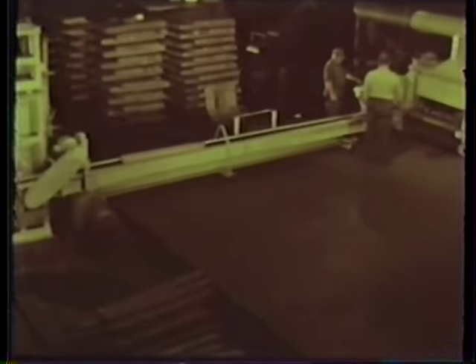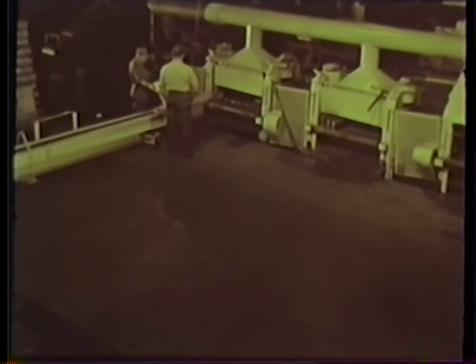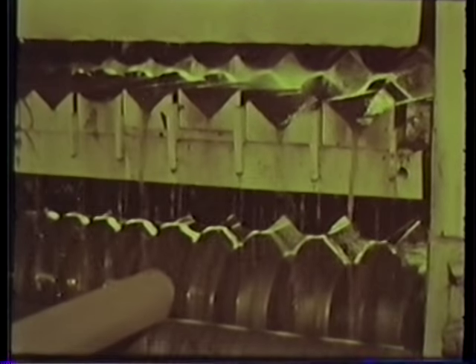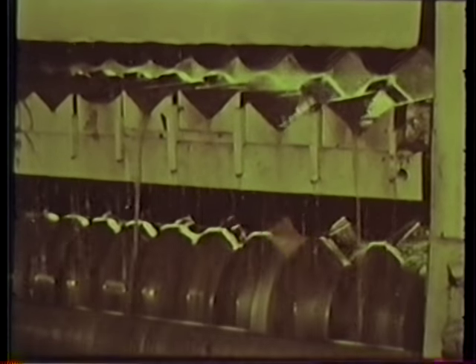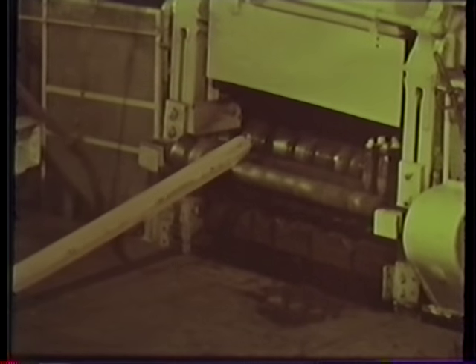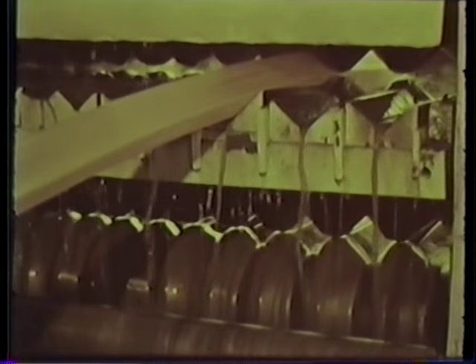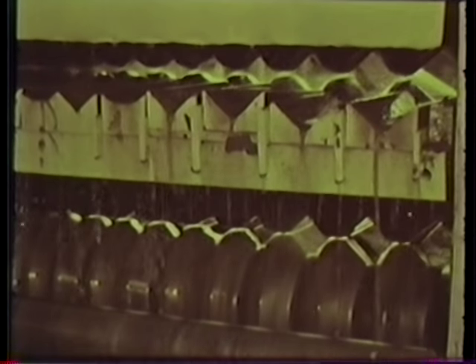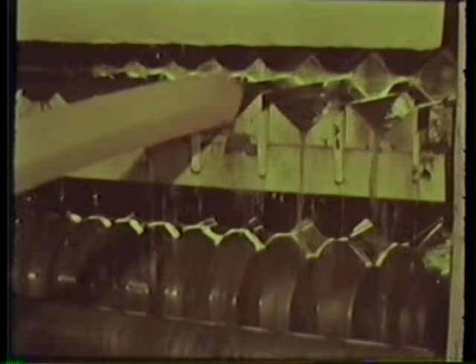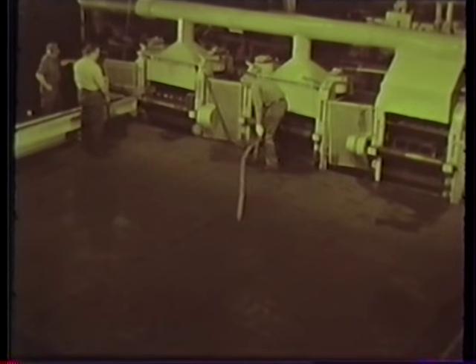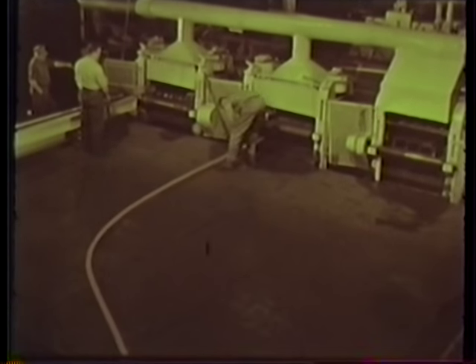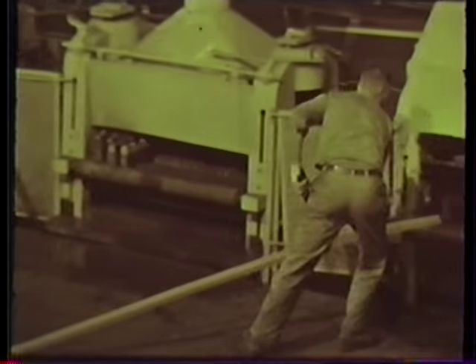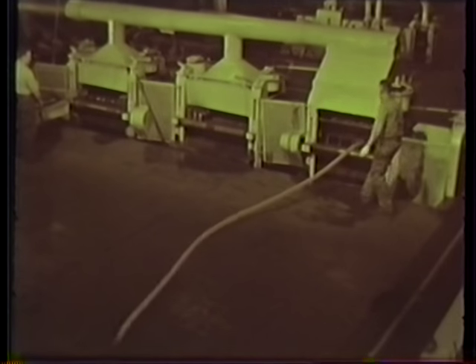The pure electrolytic silver-bearing wire bars are first heated in a carefully controlled oven, which keeps scaling to a minimum. Then through the mill for progressive sizing and application of the bevel necessary for the commutator segment's wedge shape. It's a pretty sight to watch the red-hot copper snaking through the rolls, and one you'll not see too often. For only TEMCO, of all independent commutator builders, has the volume to justify the operation of its own mill, in spite of the extra step of quality control which it affords.